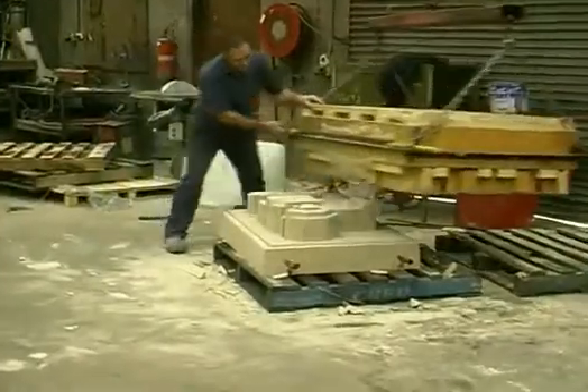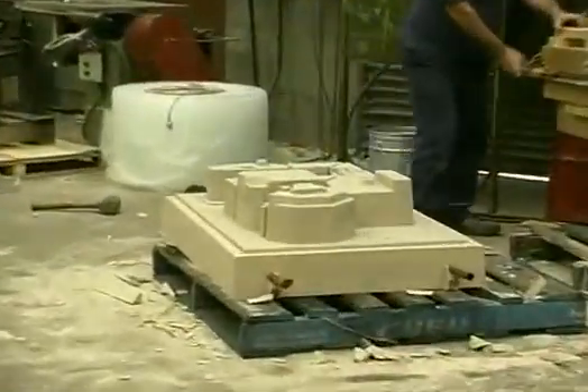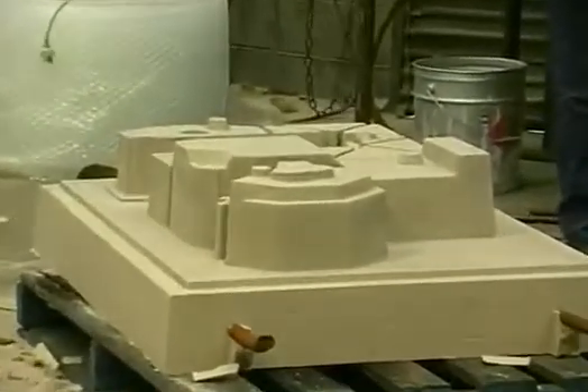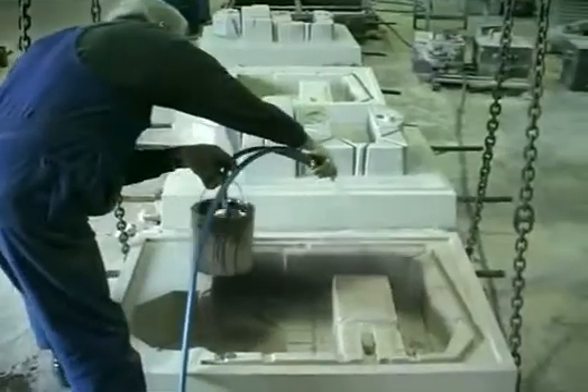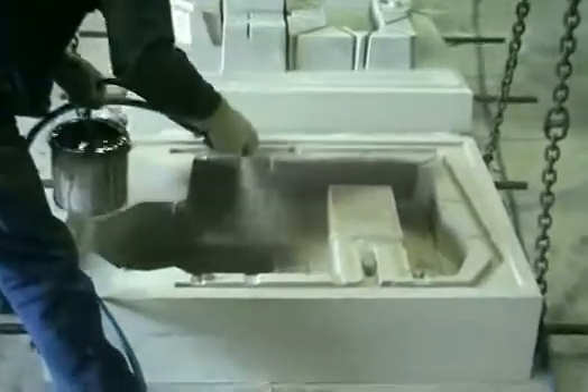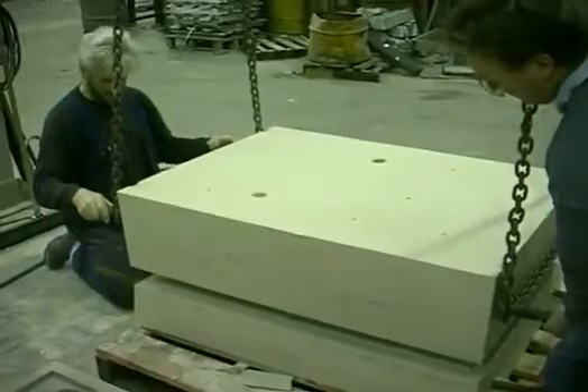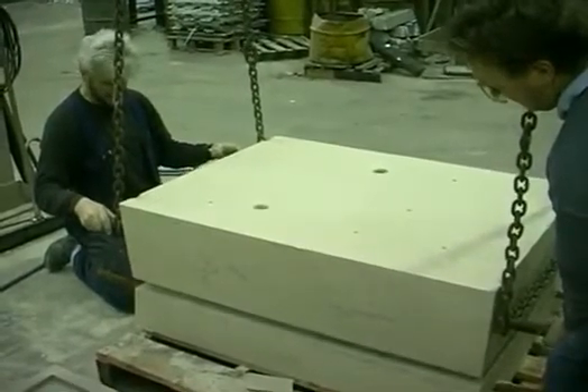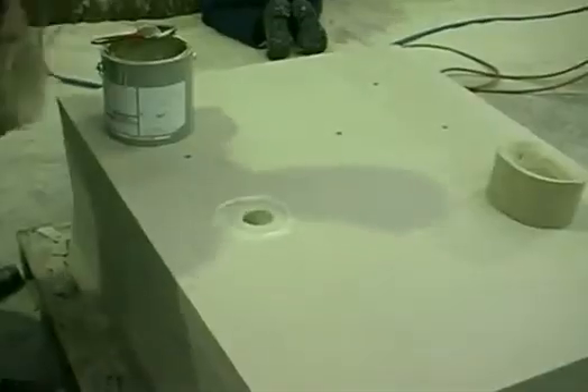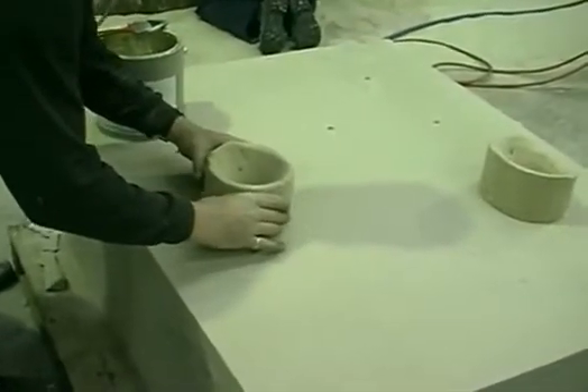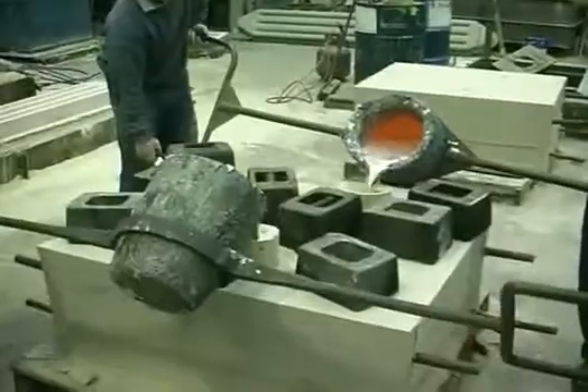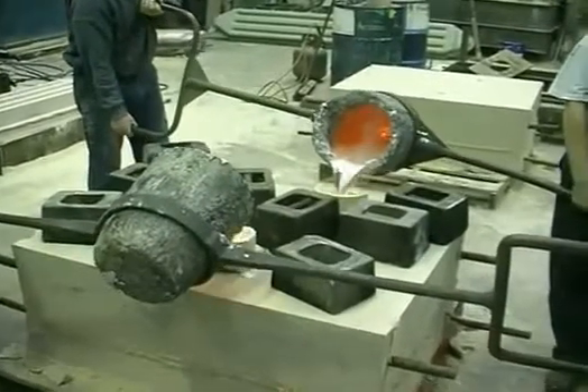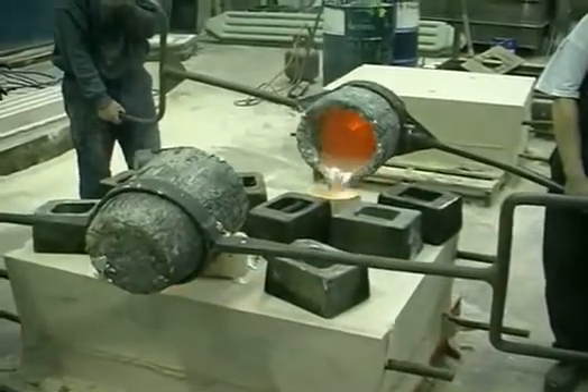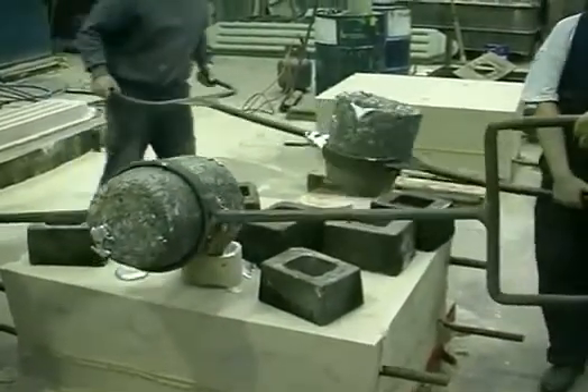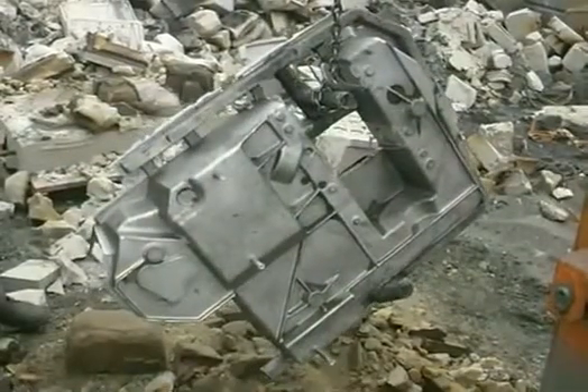Once the resin has hardened, the mould and pattern is turned over so that the pattern can be stripped off the mould. A mould coat is sprayed on to improve the surface finish of the casting. The cope and drag are carefully assembled. A pouring basin is glued onto the cope. The molten aluminium is chemically degassed just prior to pouring. The liquid metal will try to force the cope and drag apart. To overcome this, weights are added to the cope. A perfect casting.